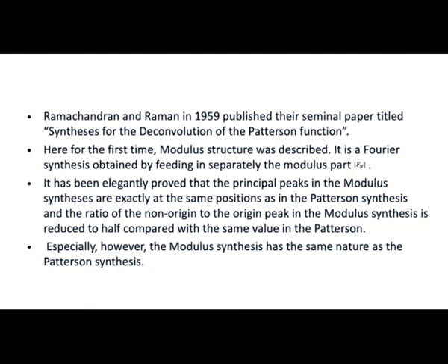It is a Fourier synthesis obtained by feeding in separately the modulus part mod Fn. It has been elegantly proved by them that the principal peaks in the modulus synthesis are exactly at the same positions as in the Patterson synthesis, and the ratio of the non-origin to the origin peaks in the modulus synthesis is reduced to half compared with the same value in the Patterson. Essentially, however, the modulus synthesis has the same nature as the Patterson synthesis.